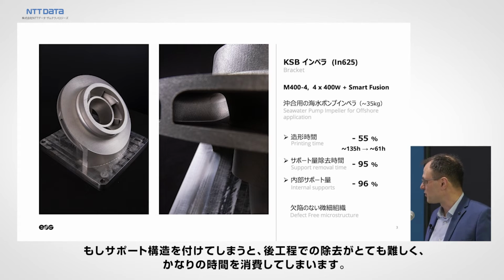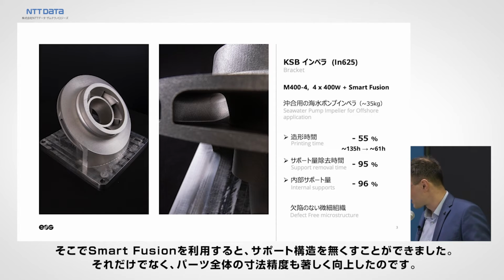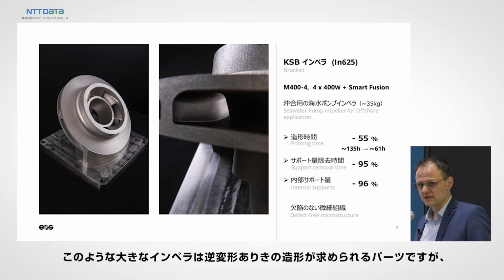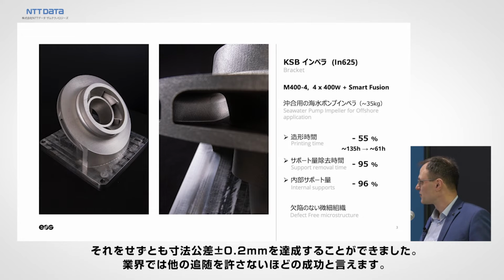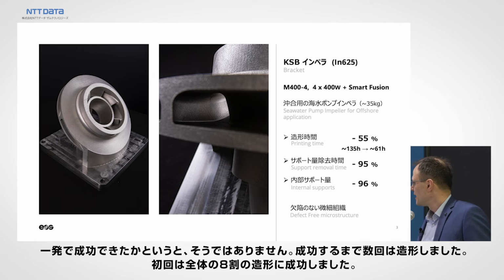If you have supports in there, the post-processing of these cavities is extremely challenging and very time consuming. So with Smart Fusion, those were just eliminated. Also accuracy-wise, we had a significant improvement in the geometrical accuracy of the entire component. So after the printing, with pre-deformation, we could achieve a tolerance of plus minus 0.2 millimeters on such a big impeller, and that is pretty much unrivaled in the industry.